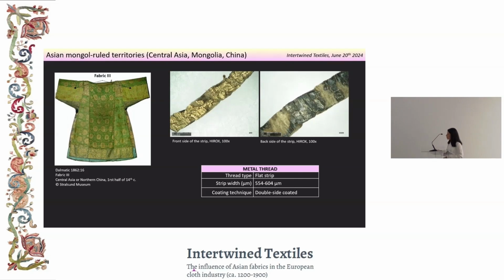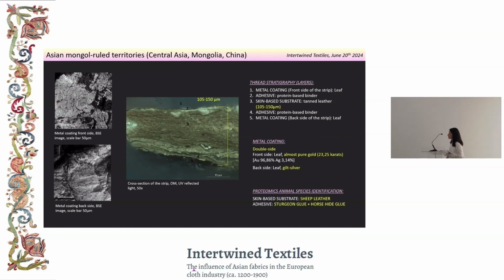So it's always a flat strip of skin-based thread, but the coating was on both sides, so on the front and on the back of the strip. And here the microanalysis has revealed that on the front side we have almost pure gold, while on the back side we found gilt silver. The stratigraphy again is kind of complex, so we have 2 different adhesive layers, in this case to join the 2 metal coatings to the strip. The strip is made of tanned leather that has been identified by proteomics again as sheep leather. But in this case, a different mixture of adhesive has been used. So we have sturgeon glue and horsehide glue.